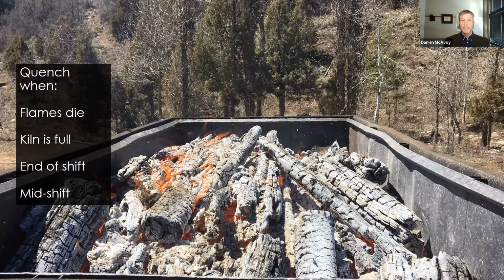Or even most practically, what I find is that we do 2 shifts in a day. We come in the morning, load the kiln, have a full burn, quench, dump just before lunch, take a little break, do the same process. So at the end of shift, we've quenched and we can walk away with no fire going overnight.